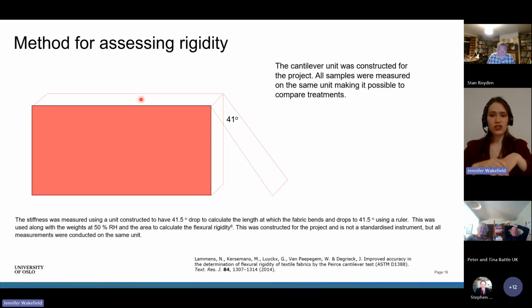Because it's self-constructed, we can't compare it to literature results, but we can compare within our own tests. Everything was done on the same unit so we could compare within our project, and we compared everything to the untreated and the water control. This could be used in any conservation lab. It wouldn't be restricted to engineering or having to buy the unit. What happens is you push the material along here, and then it drops, and you measure that drop.